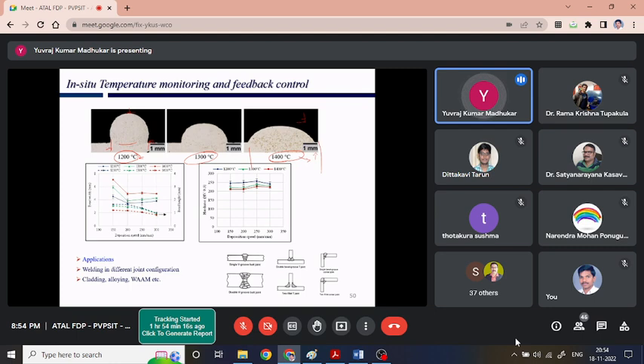Now, when we look at the mechanical properties, yes, of course, they also change with respect to the set point temperature. Here we could see in case of 1200 degrees centigrade, the hardness was high. In case of 1300 degrees centigrade, it was relatively low. In case of 1400 degrees centigrade, it was further low. That means by controlling the temperature, we can control the bead physical properties, bead width, bead height, and dimensional accuracy. At the same time, we are also controlling its mechanical properties.